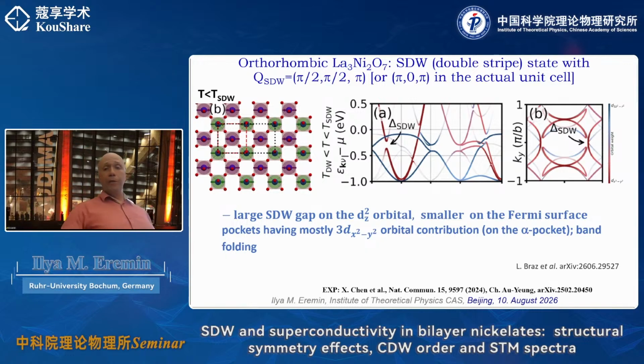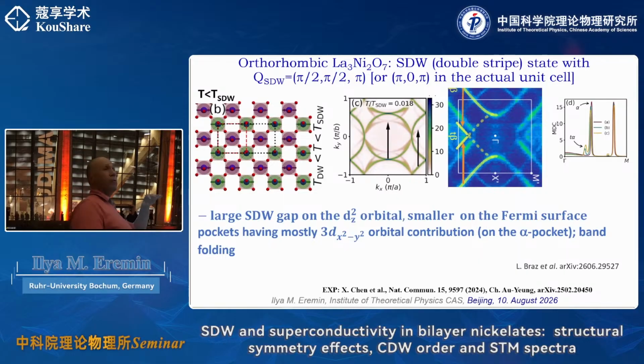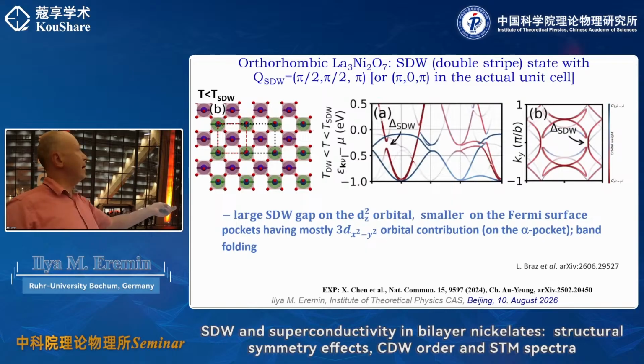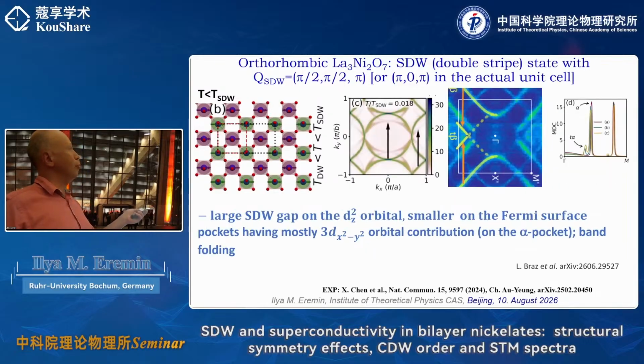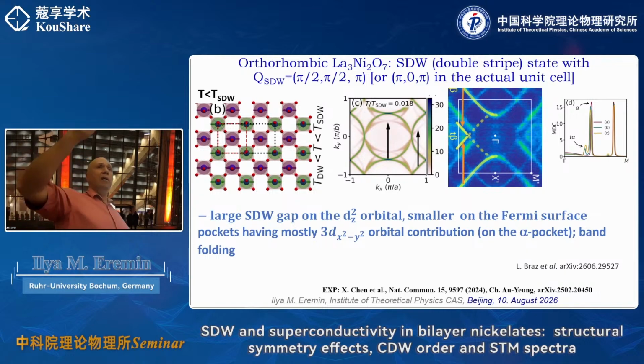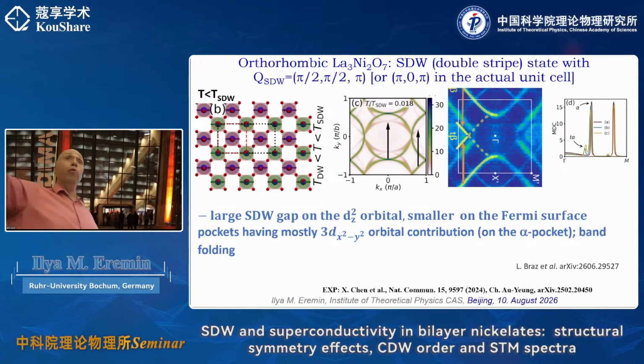And now here comes a question: how to compare it with the ARPES? To compare with the ARPES, you need to know that usually in ARPES, because of the Fermi function, they cannot really cut at a particular energy. They perform some summation. So what is shown here is really a cut at 0 energy, right? So at the Fermi energy. However, here, in order to emulate the experiment, we actually integrated out a narrow spectral weight. So we integrated out plus minus 30, 40 meV. We integrated the spectral function and then plotted its normalized sum. So this is what would be something like a Fermi surface map in ARPES. And then you compare again.